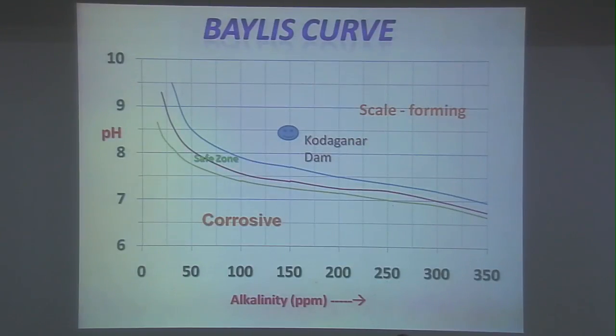Of course, when the test results of the Kodaganar Dam are plotted over the Baylis curve, actually the Baylis curve can be applied for waters with high pH and high TDS. Of course, the Langelier index can be followed for low pH, low TDS, particularly where TDS is less than 1,000 parts per million. Here, Kodaganar River has high pH and high TDS, so we have followed the Baylis curve.